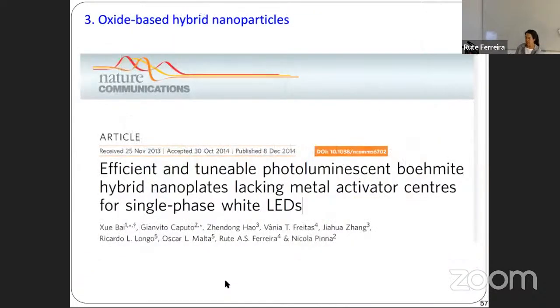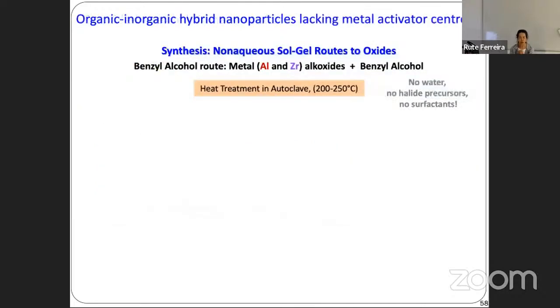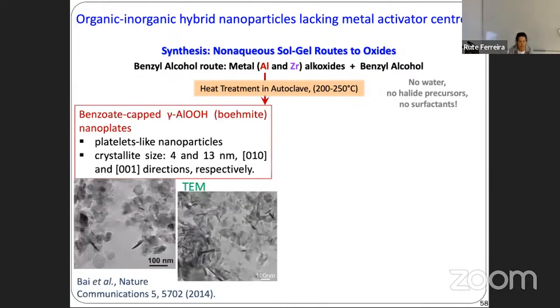So the last example that I would like to show to you today is the case of oxide-based hybrid nanoparticles that were also prepared by the sol-gel non-aqueous routes. This time we decided to use two metal alkoxides, aluminum and zirconium, plus benzyl alcohol. So the benzoate boehmite nanoparticles are in fact platelet-like nanoparticles. They have a crystalline size of 4 and 13 nanometers.